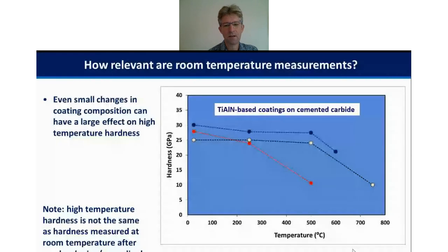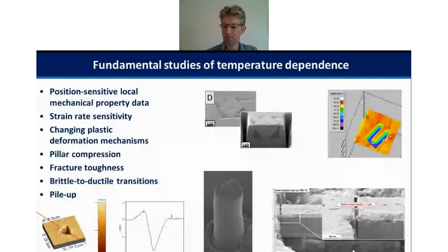And I should also say that in all the graphs that follow, when I put temperature on the x-axis, this really means test temperature. This is not a question of heating the sample up and then cooling it back down and remeasuring after an annealing temperature. This is the temperature we do the test at. So this is a good example that typically you anneal things to make them harder, but when you test them at temperature, the hardness still typically drops.